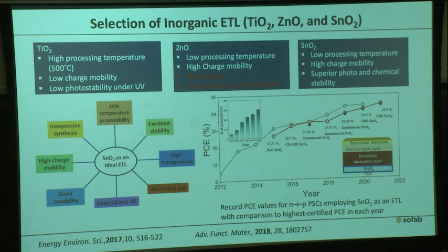Plastic-based flexible substrates have a melting temperature above 120 degrees Celsius. Also, titanium dioxide undergoes a photocatalytic reaction in the presence of UV radiation, which causes degradation of the perovskite as a whole. After that, to solve this, people started using zinc oxide.